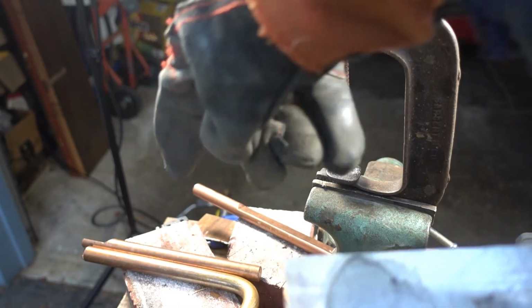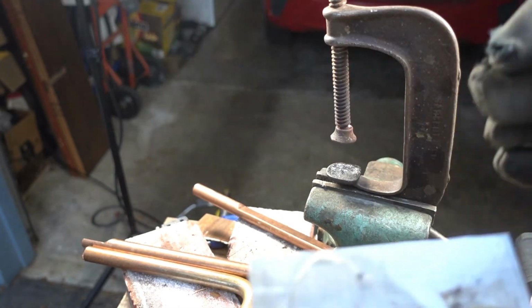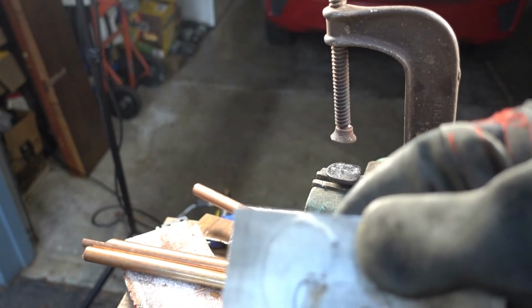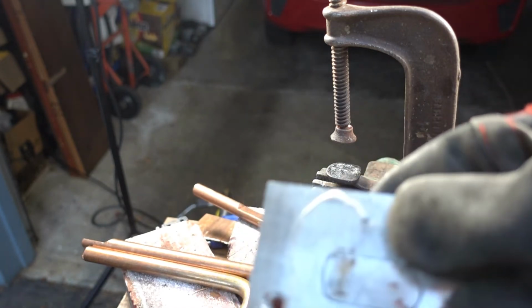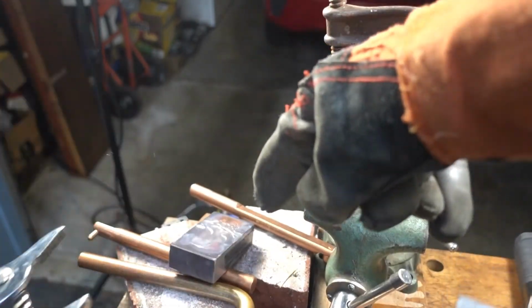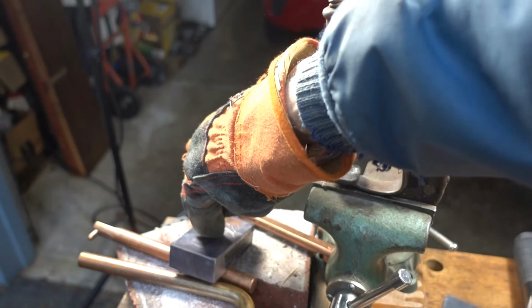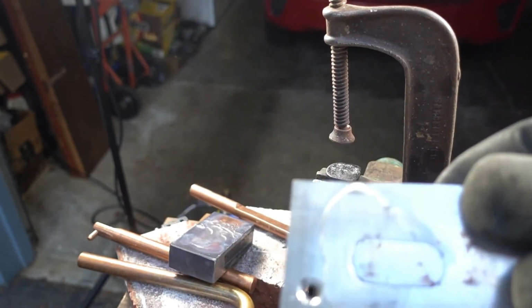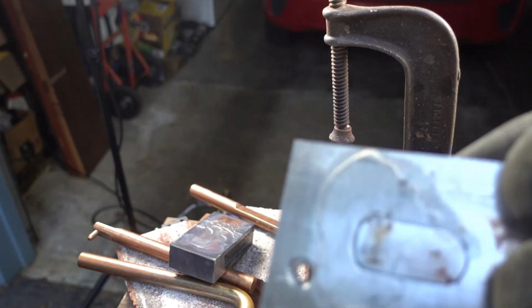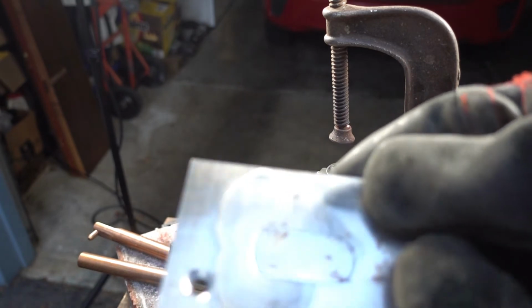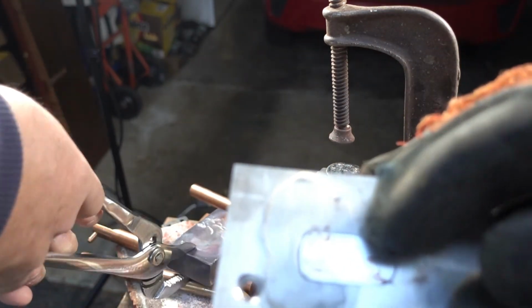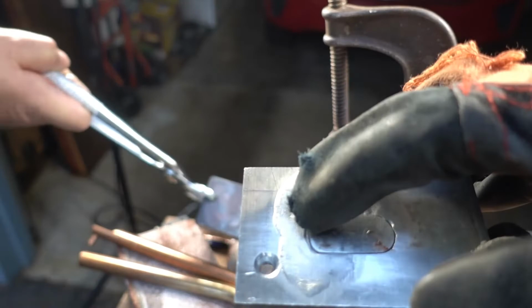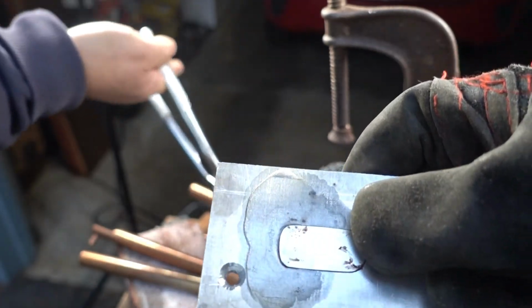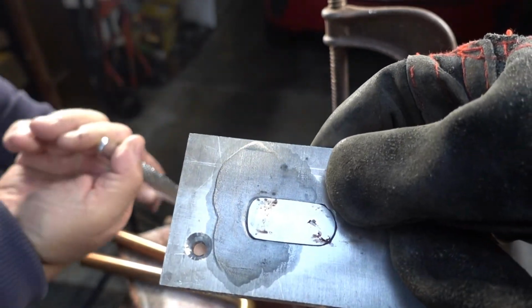Okay. This big piece of copper, there's a copper bar here that we used as a backer. I think that took a lot of heat out of this. This copper bar is still very hot, but it's a huge piece of copper, and that acted as a huge heat sink. 1 inch thick. But we did expect to see the aluma weld in the underside of this groove, and it really didn't happen.